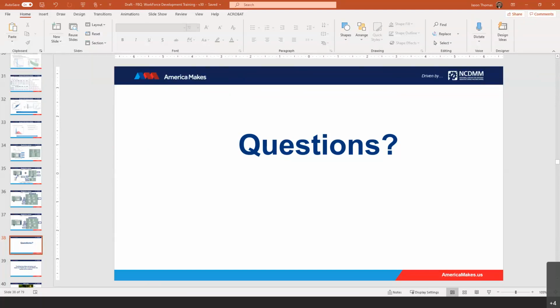Yes, Neil. So the mechanical testing criteria was based on the fact that we were targeting at least a range around the as-cast values. So that was our target numbers. And we were basically extracting the samples from the walls that were buildable. So let's take a top-down approach. We define a build space, a build parameter, and we go ahead and build it. If we are successful in building a particular size and shape of the wall, we kept the height and the length of the wall constant, 6-inch tall and 10-inch wide. And the width of the wall was dependent on the build parameter of choice. Once we were successful building to a certain height of the wall, we thought it's a success. And then we could extract the samples based on the location specific to the wall itself.